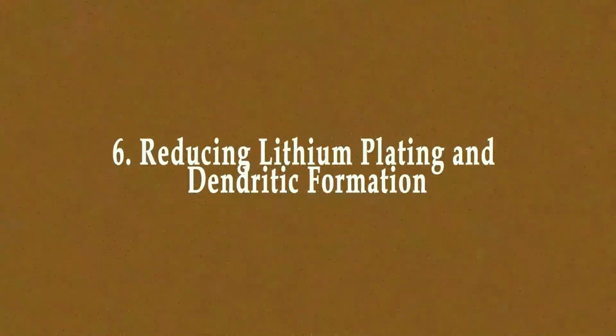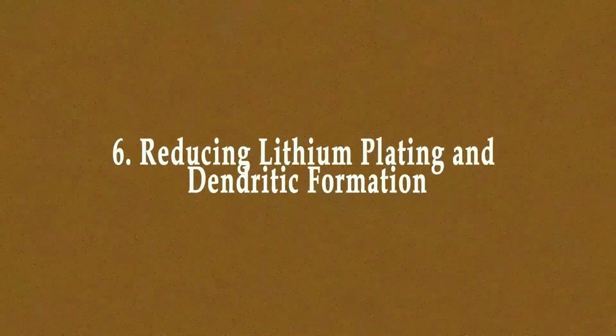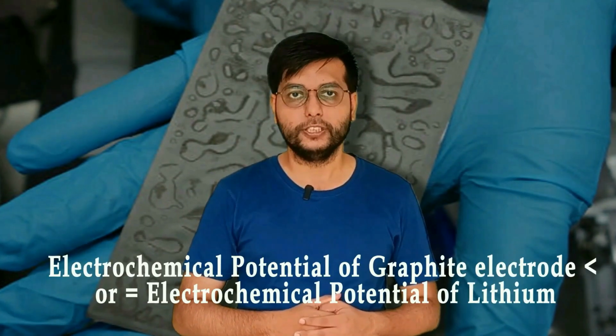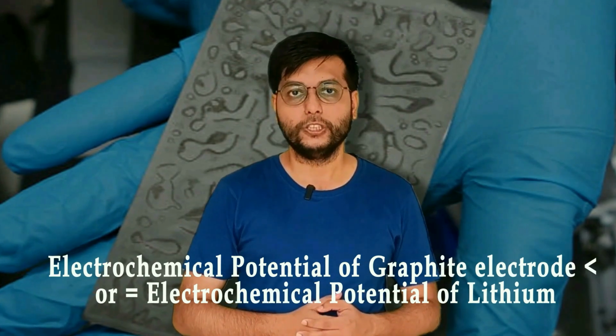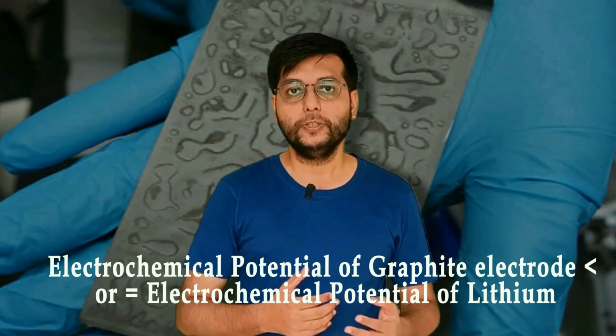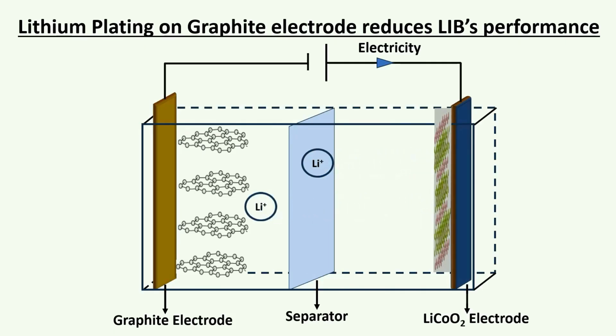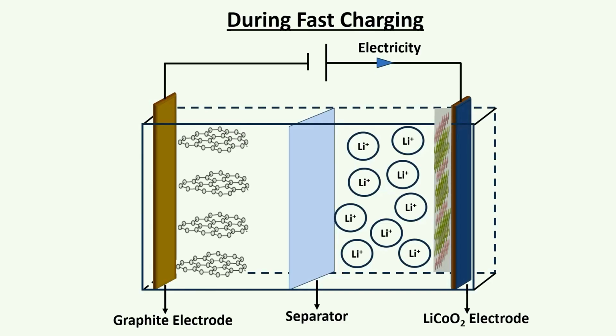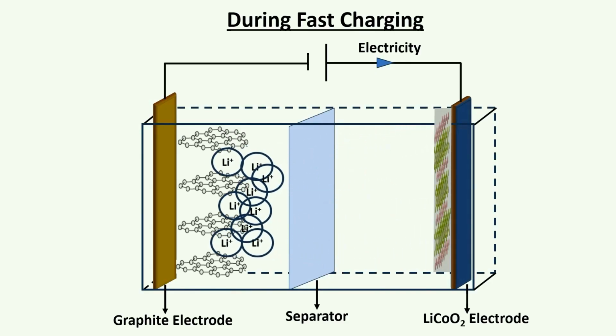Challenge number 6, reducing lithium plating and dendritic formation. Lithium plating occurs when the electrochemical potential of the graphite anode is equal to or lower than the potential of the metallic lithium. This means that the lithium ions that arrive at the graphite anode cannot distinguish the anode material from the metallic lithium and deposit in the metallic form rather than the desired intercalation within the spaces between the graphene sheets.